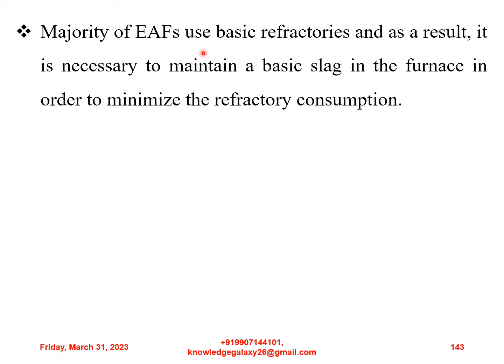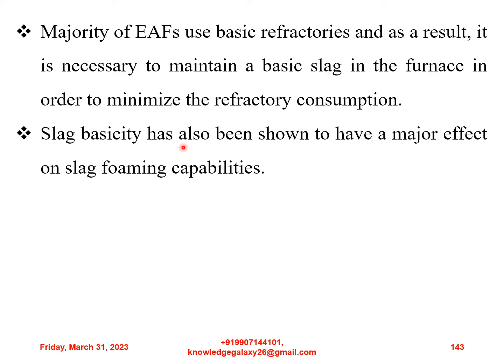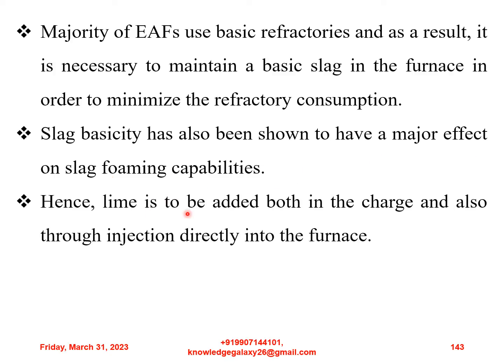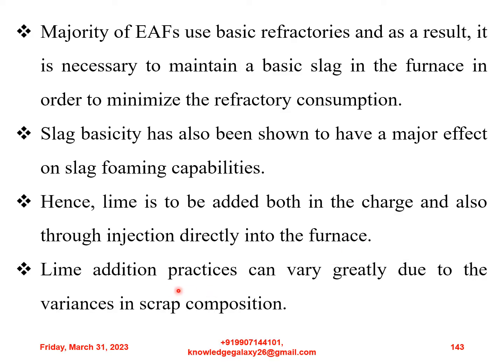Majority of the electric arc furnaces use basic refractories, and as a result, it is necessary to maintain a basic slag in the furnace in order to minimize the refractory consumption. Slag basicity has also been shown to have a major effect on slag foaming capabilities. Hence, lime is to be added both in the charge and also through injection directly into the furnace. Lime addition practices can vary greatly due to the variances in scrap composition.